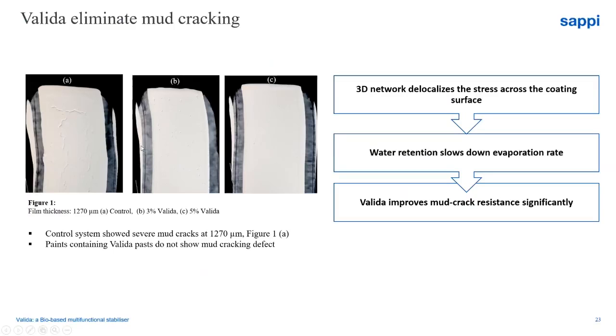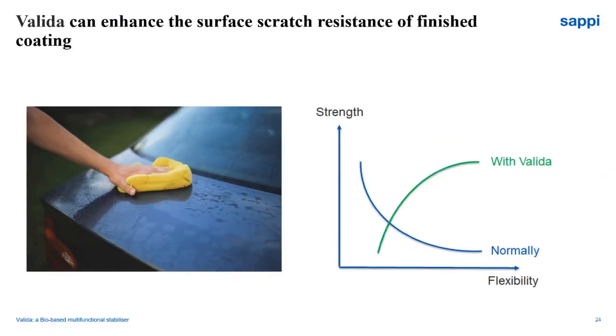We have proven results that Valida reinforces polymers and coating layers, and I'm happy to share with you also one interesting learning. Generally speaking, when the stiffness increases, we have noticed that the flexibility decreases. Well, when adding Valida, we have seen very surprisingly that it's able to improve either the stiffness but also the flexibility, which is quite a rare combination to have.